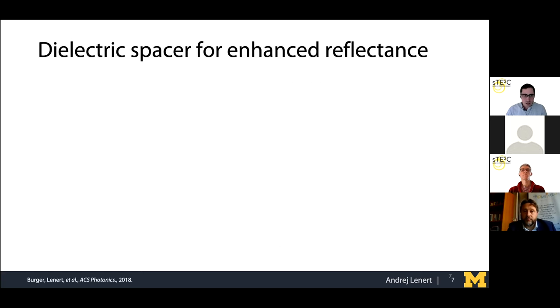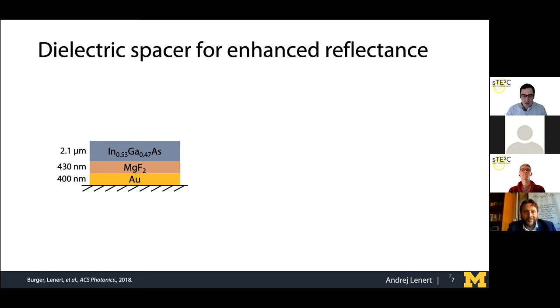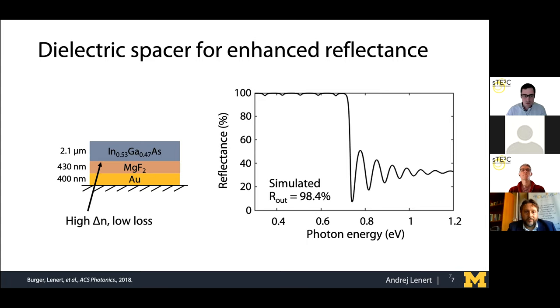So this theoretical consideration has really framed the work that we've been doing with Steve Forrest and in my group. So one of the first things that we tried to do to increase the reflectance compared to that conventional thin film structure that the Berkeley group achieved was to create a low index spacer, magnesium fluoride, between the absorber and the gold layer. And in principle, if we look at an interference calculation, we can see that the out-of-band reflectance can be as high as 98.4%.